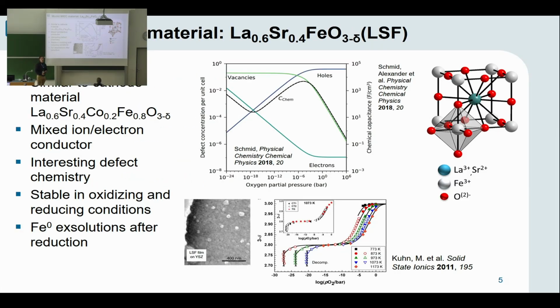Overall, we are very interested in the defect chemistry of these materials because this is a very decisive property for the electrochemical functionality of the materials. And one very often used prototype material is lanthanum strontium ferrite, or LSF, which is an acceptor-doped perovskite material.